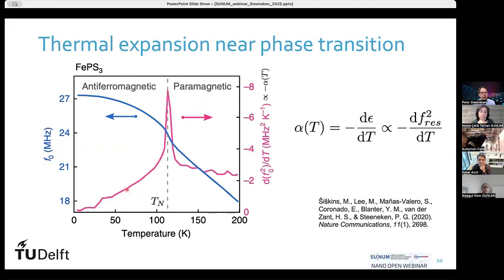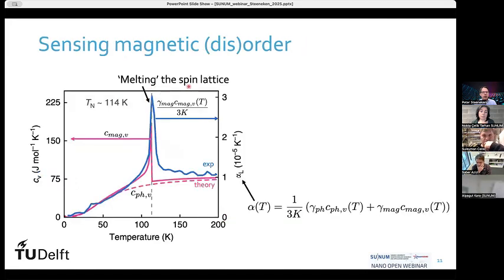So if you start heating the material, here it's still magnetic, but around this temperature, you have to add a lot of energy to still break this magnetic order that is there in the structure. It's a little bit like melting an ice cube. So around 0 degrees Celsius, you have to put a lot of energy to melt the ice cube. And this peak here is basically a peak in a specific heat, which means you have to put a lot of energy to, in this case, melt the magnetic spins. So you're melting the spin lattice. So this shows that with these magnetic resonance measurements, we can actually study those magnetic properties of this material.